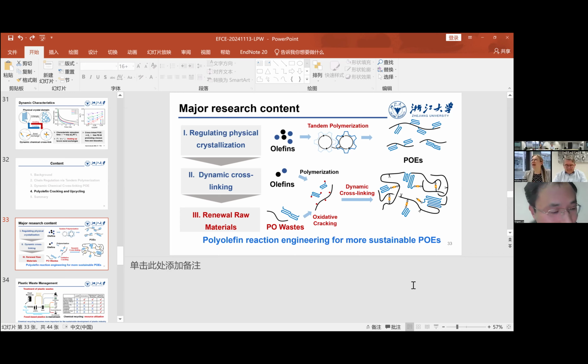I was wondering, how did you mimic the recycling of your materials? Did you extrude them, or did you just cut them and hot press them? Did you stabilize them somehow? So for the experimental demonstration in our paper, we just took these materials, cut them into very small pieces, and then did the hot processing. So this is one way we show the reprocessing. And for this part of work, we actually did some extrusion reprocessing. Okay, so there's a difference.